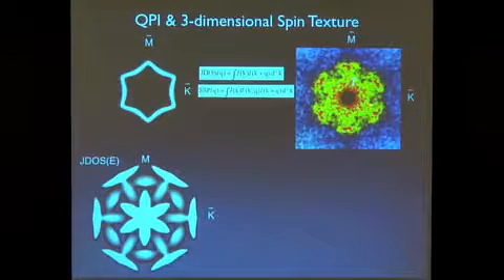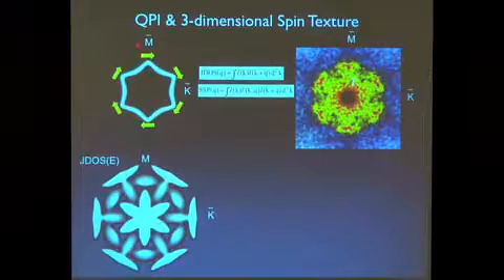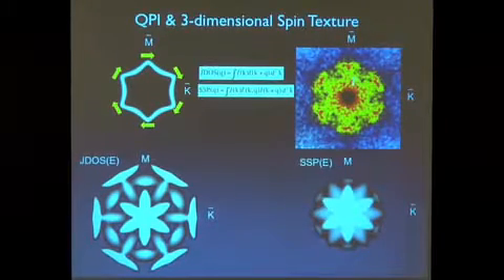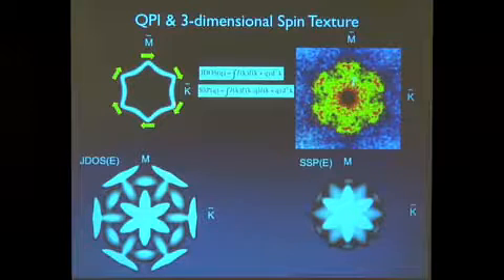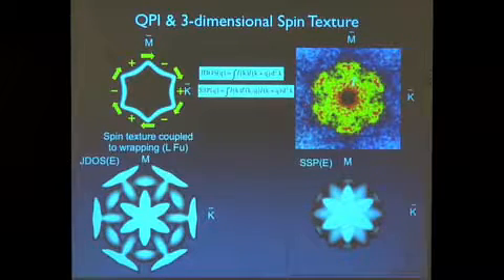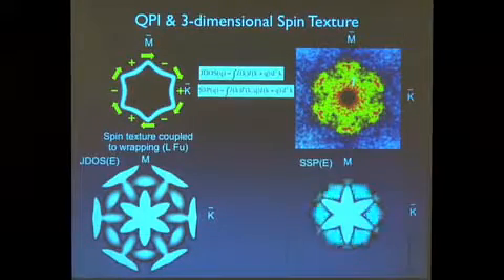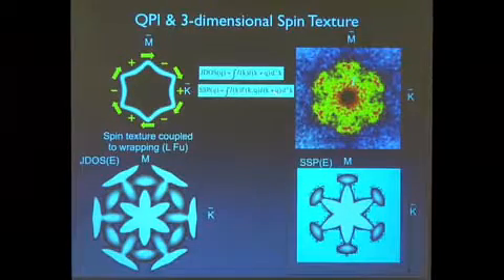You get something that doesn't look like the STM data. If you add in the spin texture, you do a little bit better. But actually, you find that you don't quite get there. And this has to do with the fact that because there is spin-orbit coupling, when the K states have curvature that's basically shown as this snowflake structure shows, you actually have a slightly different spin signal, as well as in plane. You have a slight out-of-plane signal that actually oscillates around the Fermi surface as you go around. And this turns out to be a key factor to include basically in your scattering wave vectors in order to actually match the experimental data.